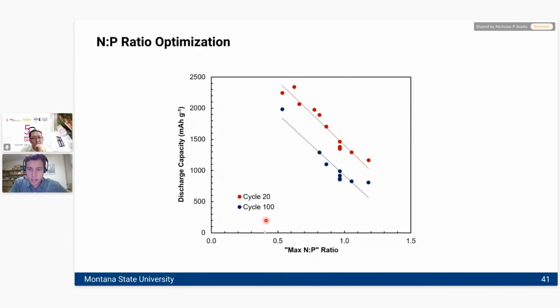And what we see is that as the loading on the anode side increases, that means the NP ratio goes up, and the discharge capacity of that electrode goes down. As we thicken up our electrodes, this is common among any kind of active anode or cathode material, but the severity of this is pretty marked. So it's important to note that our cells are only really working well when they're very thin.